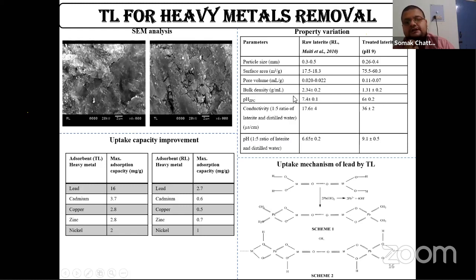The main part over here is to look at the isoelectric point, that is the pH at zero point charge. It was initially 7.4 for raw laterite, whereas for treated laterite it was 6. There is a certain theory to this. If your operating pH is lesser than the isoelectric point, then the surface will become positive, and if it is more, then the surface will become negative. As our treated laterite has a pH of 6, if we operate at a pH of 7 or 7.5, which is usually the normal drinking water pH, our surface will become negative.